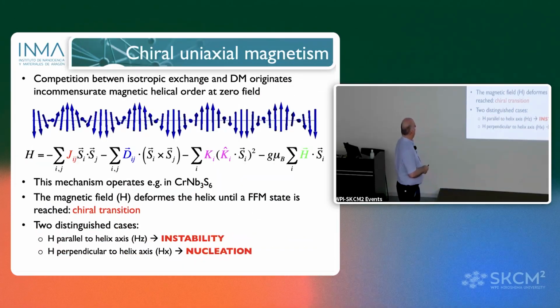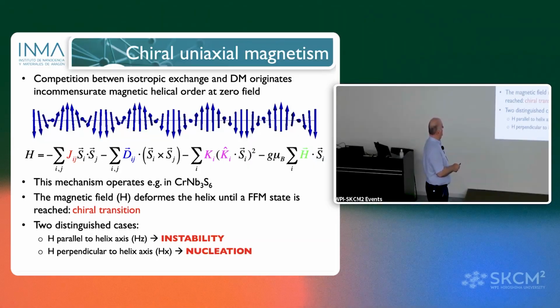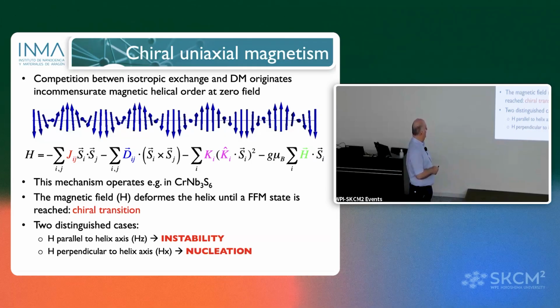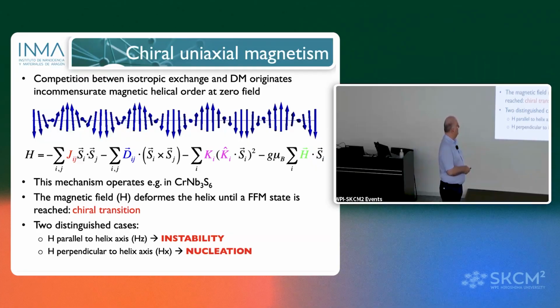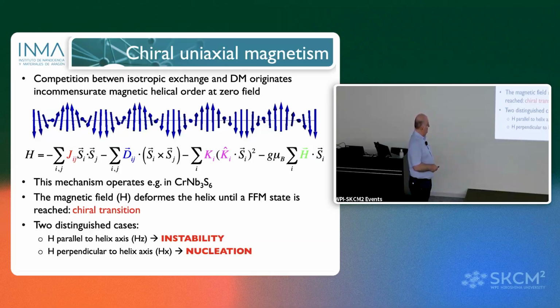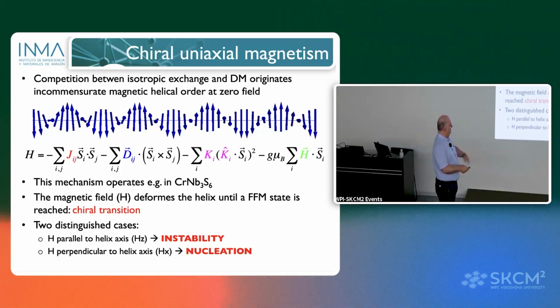In one dimension, let's start in one dimension. We have this helix, and the Hamiltonian that describes this helix is here. We have, in the discrete model, an exchange interaction term, the Heisenberg term, and the Dzyaloshinskii-Moriya. This one to align parallel or anti-parallel the spins. This one to align 90 degrees the spins. We can include one anisotropy in a given direction, and the Zeeman term. And this Hamiltonian describes very well what is happening in the uniaxial helimagnets, for example, chromium niobium disulfide, in which if you apply the magnetic field parallel to the helical axis, this axis, you will form a kind of cone that at the end will produce a phase transition called instability phase transition.